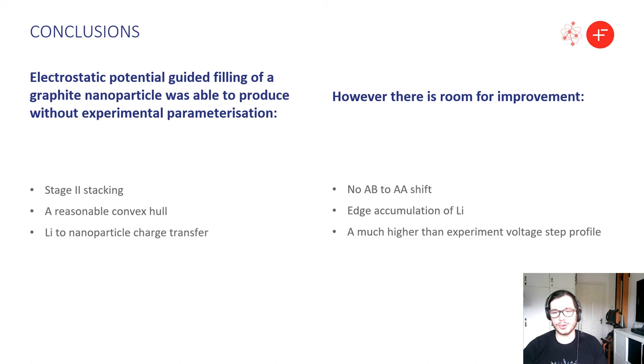To conclude, our electrostatic potential guided filling of a graphite nanoparticle was able to reproduce without any sort of parameterization or guidance from us stage 2 stacking, a reasonable looking convex hull which is very important, and lithium to nanoparticle charge transfer which is all things that we would expect to see on a bulk structure or expect to see experimentally.